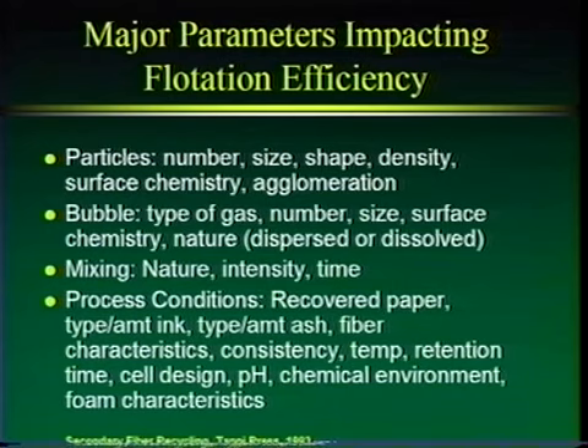Okay, just kind of as a review, major parameters impacting flotation efficiency. What you notice is that the flotation process is a little bit more complicated than washing. We've got a lot of considerations. It's a very elegant way of separating ink from fiber, but we've got a lot of considerations. So we can think about the particle characteristics: the number, the size, the shape, the density, the surface chemistry, and if they've agglomerated or not, all have an impact on flotation efficiency.